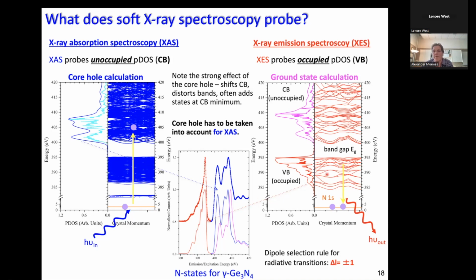So what I have not told you is the other aspect. Why do these calculations look so different, although they are for the same material, gamma germanium nitride? They look so different because this is a ground state calculation, the right one. This means in the final state of the emission process, you have a ground state with 2 electrons in the 1s shell of nitrogen completely filled. In the final state of the absorption process, there's the effect of the hole, which strongly disturbs and perturbs the band structure. So the difference between the blue and the red calculation is: left side excited calculation, not a ground state calculation; right side ground state calculation.